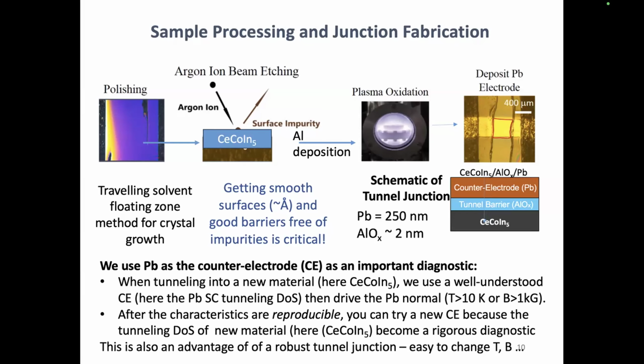One of the reasons we use counter electrodes of lead or a known superconductor is because we don't understand what's going on, whether it's a cuprate, a heavy fermion, or some interesting material. And if we use a counter electrode of a material we do understand, we could look at the quality of the lead tunneling conductance to have a gauge on the quality of the junction to see if we're really getting single-step elastic tunneling.